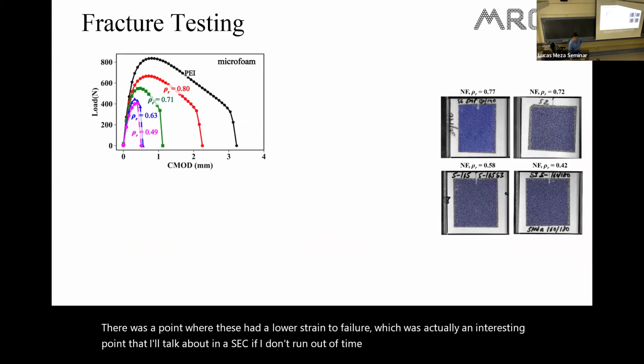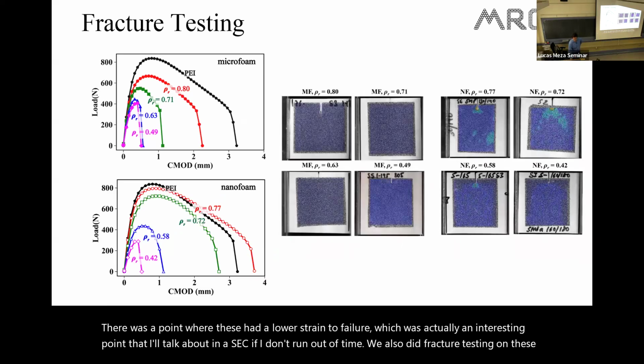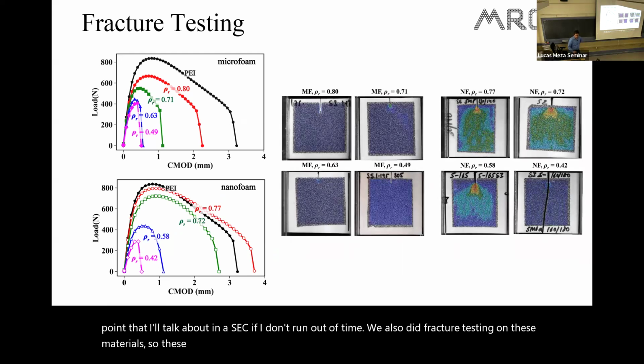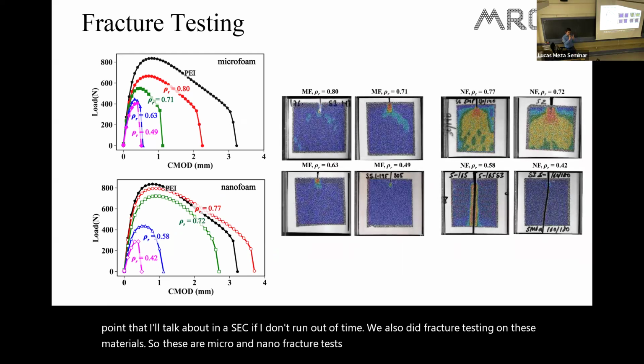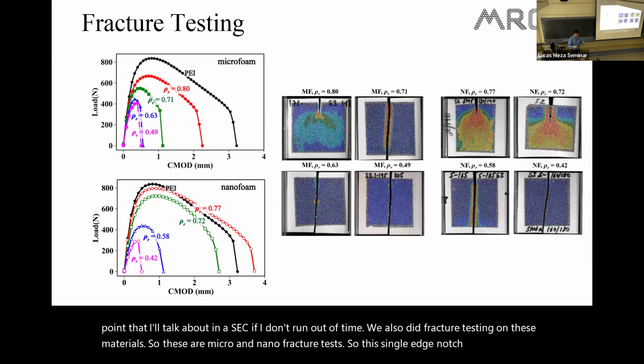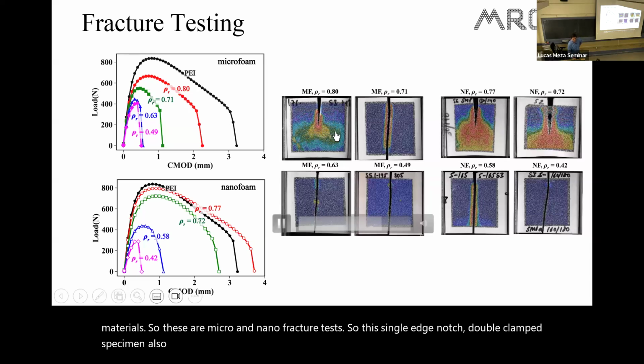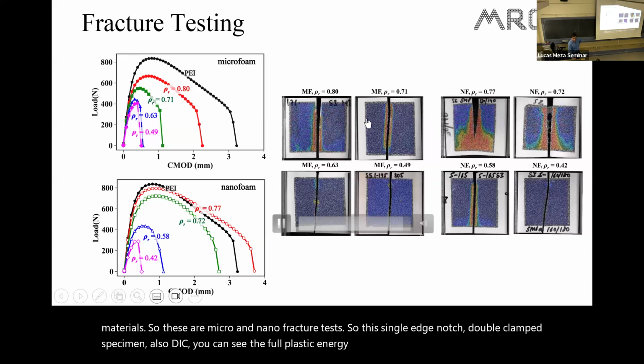We also did fracture testing on these materials. So these are micro and nano fracture tests, using a single edge notch double clamped specimen, also with DIC. You can see the full plastic energy field as this dissipates.